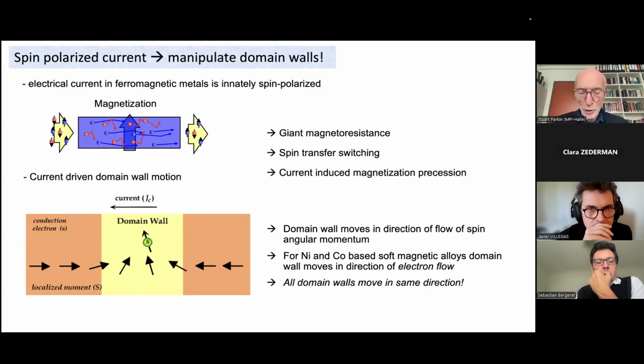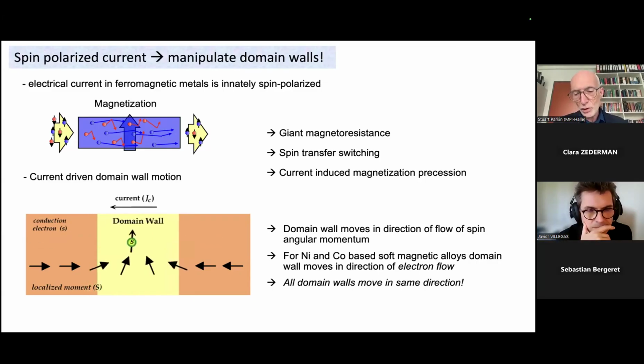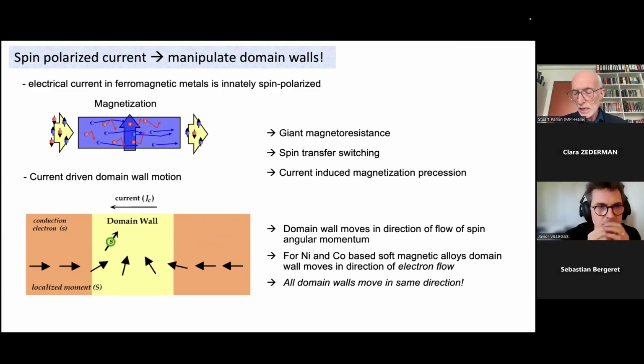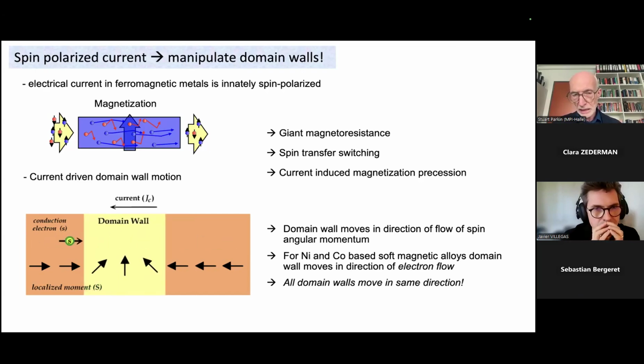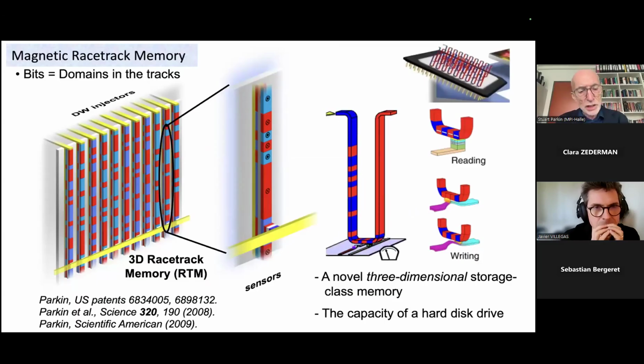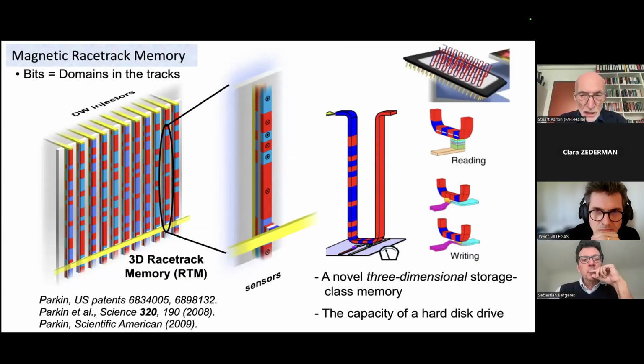And what I proposed was that if we have a series of domain walls, all those domain walls will move in the same direction by current pulses. And this is something that we first demonstrated in 2008. And then this is the concept. This is the racetrack memory, that if we have a vertical magnetic wire shown on the right-hand side or on the left-hand side, then this vertical wire can be magnetized in the red and blue directions. And by passing current pulses into the racetrack, you can move a series of magnetic domain walls around the racetrack, and one would move them towards elements for reading and elements for writing domain walls integrated into that racetrack.